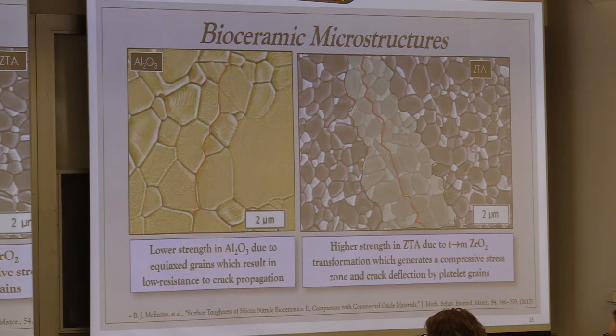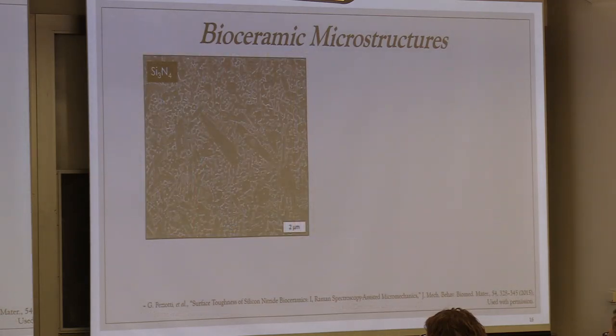So now let's contrast that to, say, silicon nitride. So here's a silicon nitride microstructure. You can see now, instead of equiax, it's very fibrous. Some of the grains have the C-axis perpendicular to the plane that you can see, and some are parallel, so you can see what it looks like. So you can have these elongated, fibrous-like grains. As cracks propagate through this intergranularly, it's a very tortuous path that they have to follow as they go through. And what happens is that some of these grains actually bridge over the crack and keep it from expanding.